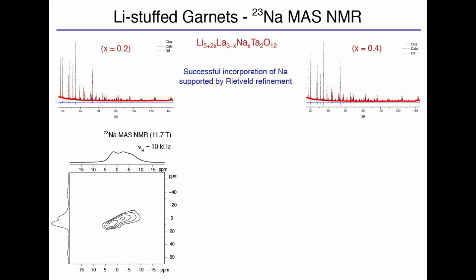So this is an example where we can use those two-dimensional techniques I talked about at the very start of my talk. And remember, we read these two-dimensional maps as if it's like a contour map if we're hiking in the Lake District. So we're looking at the number of ridges that we have. Now in this case, it's quite difficult to really see if that's one or two, but if you look at the projection on here, you can see that it looks like there's two distinct peaks. And we can extract parameters for these two peaks that tell us a little bit about those sodium environments. But the main thing is that this sodium spectrum has indicated we have definitely got sodium into that structure. So again, it's a bit of a tick to say it confirms the diffraction data.